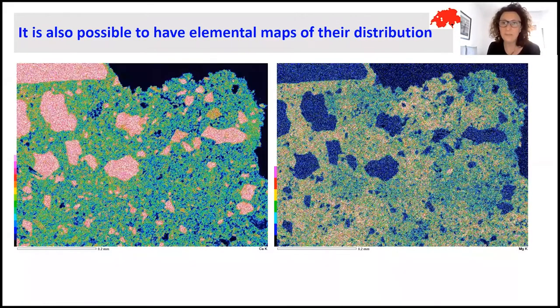Another possibility offered by the scanning electron microscope is to obtain elemental maps in order to see how the different elemental composition is distributed within a thin section. For example, here we have the distribution of calcium in the left image, and we can say that we have a medium presence of calcium in the binder and a higher presence of calcium in the aggregate. On the contrary, in the right image, we see the distribution of magnesium, and in this case, we have a medium quantity of magnesium within the binder and the absence of magnesium within the aggregate.